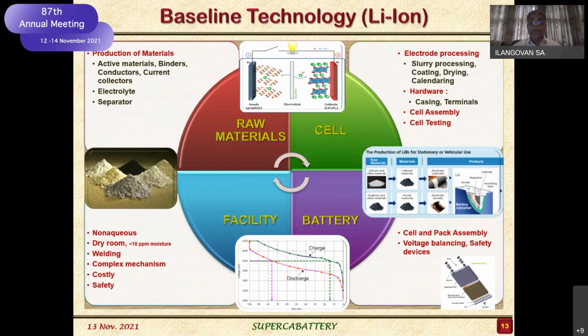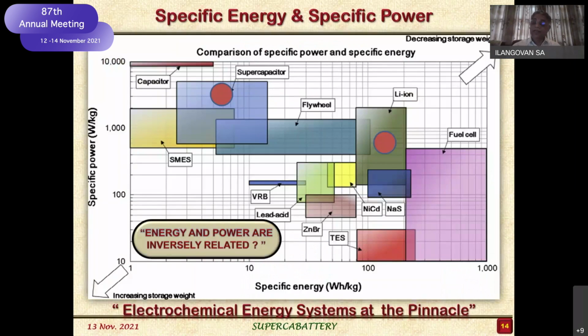So what is the problem? What is it I'm trying to say here? I'm still crippled. See, the supercapacitor is somewhere here. If I look at it, the power is very good. We are able to touch the order of about 4 or 5 or 6 kilowatt per kg. But the problem is that energy-wise, it is very poor. When it comes to lithium-ion battery, I have energy, maybe nearly 10 times or 20 times more. But still, when it comes to power, it is about 1/5 only. So that's the combination of aspects. So developing the battery, but power is not there.